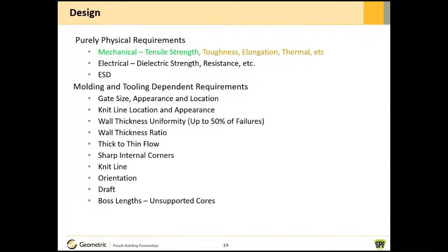Going back to design, looking at the same thing from the metals world, we look at the tensile strength, toughness, elongation, etc. But in the plastics world, we have to look at the electrical properties, electrostatic discharge, ESD properties. We have to look at the molding and tooling dependent requirements. We have to look at the gate size, appearance and location, knit line locations, appearance, wall thickness uniformity, wall thickness ratio, thick to thin flow, sharp internal corners, knit line, orientation, draft, boss length. All of these will affect the ultimate performance of our plastic parts. And we, as the mechanical engineers, designers, have to look at that.